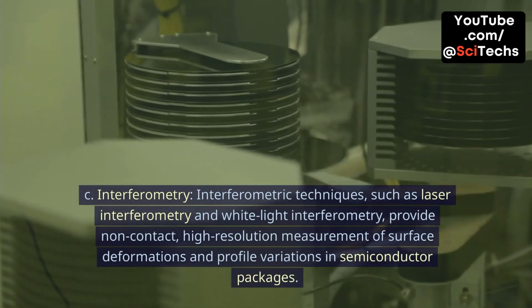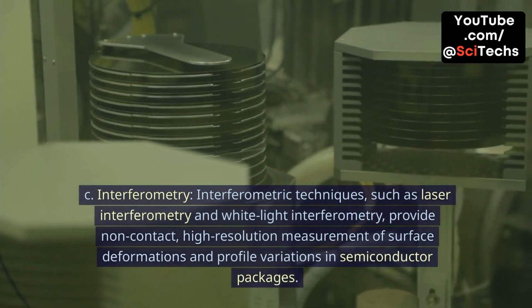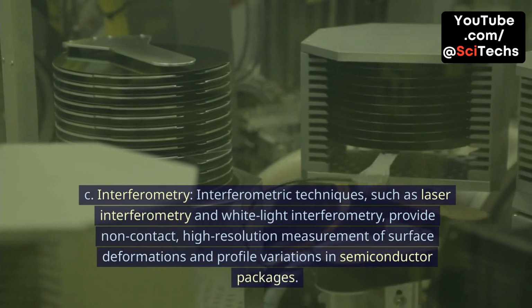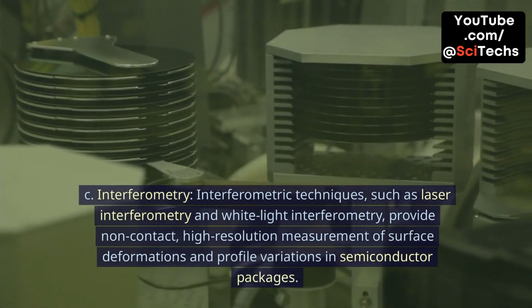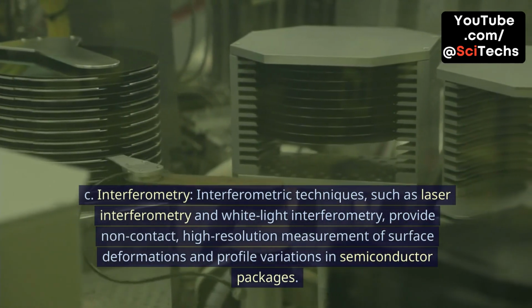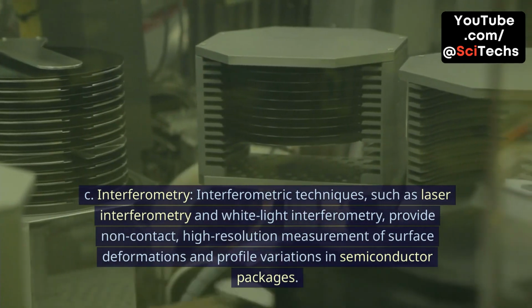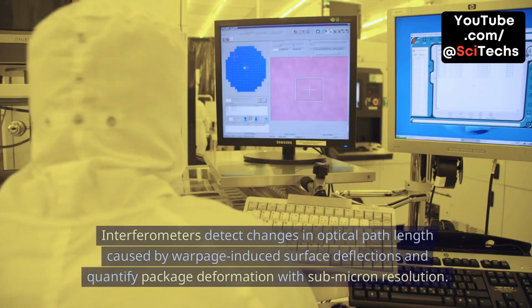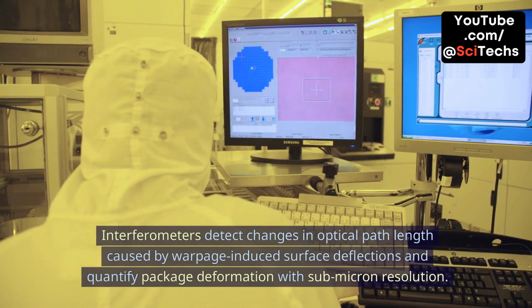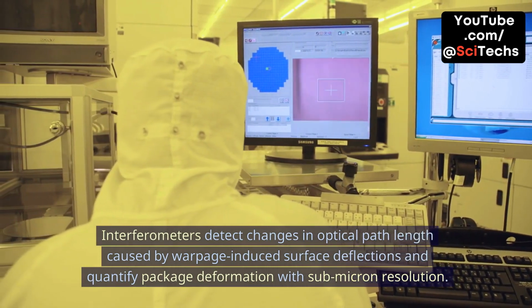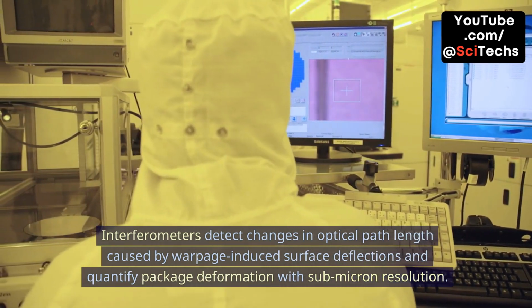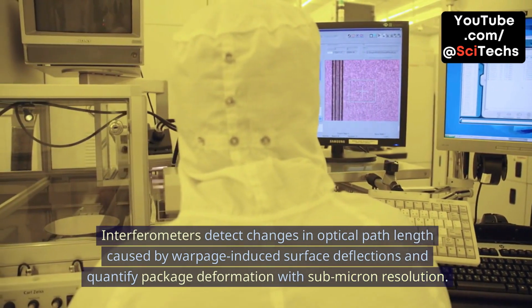C. Interferometry. Interferometric techniques, such as laser interferometry and white light interferometry, provide non-contact, high-resolution measurement of surface deformations and profile variations in semiconductor packages. Interferometers detect changes in optical path length caused by warpage-induced surface deflections and quantify package deformation with sub-micron resolution.